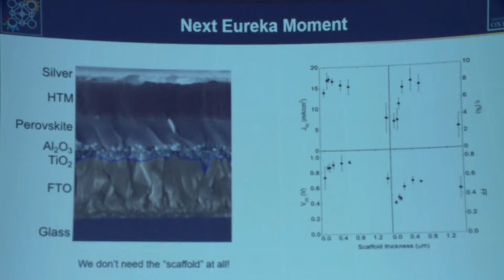This was a surprise, because up until this point I'd been living by the notion that we needed this interdigitated bulk heterojunction, porous structure, for any of these cheap and easy materials to work. Suddenly we've got a solid absorber that's just processed and dried at 100 degrees centigrade and seems to be working better. So as we went thinner and thinner in the scaffold, the efficiency got better and better.